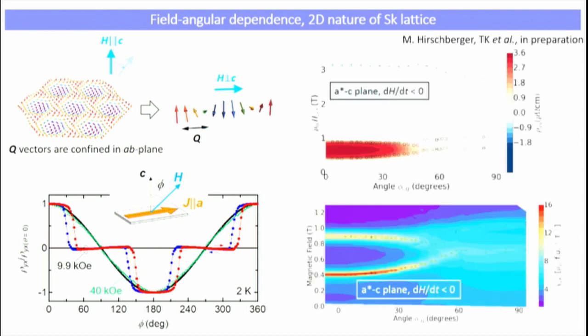This is a phase diagram of the topological Hall signal, as well as the magnetic phase diagram determined by the susceptibility. Only when the field angle is lower than 60 degrees does the A phase region appear, suggesting the stability of the two-dimensional spin texture only in magnetic field around the C-axis.